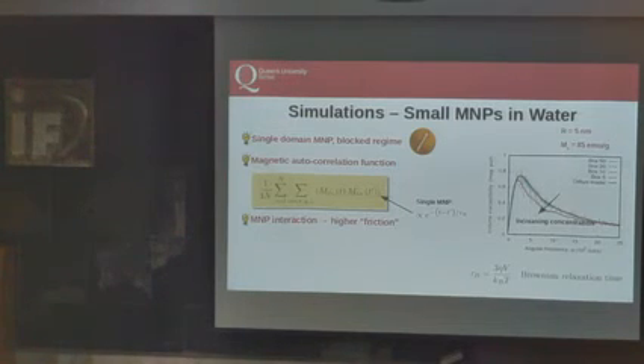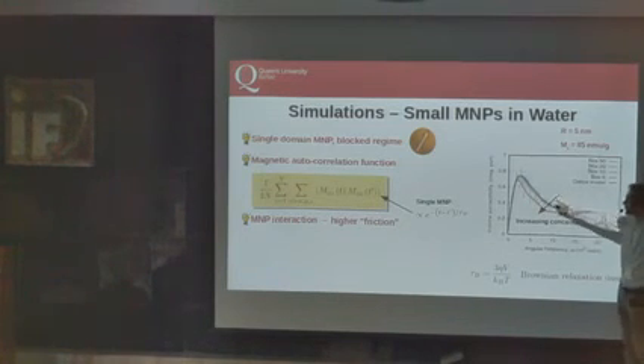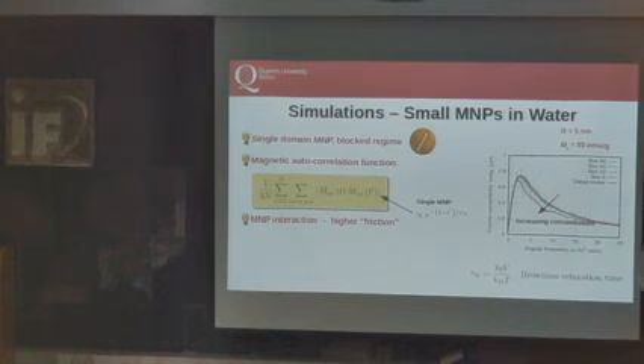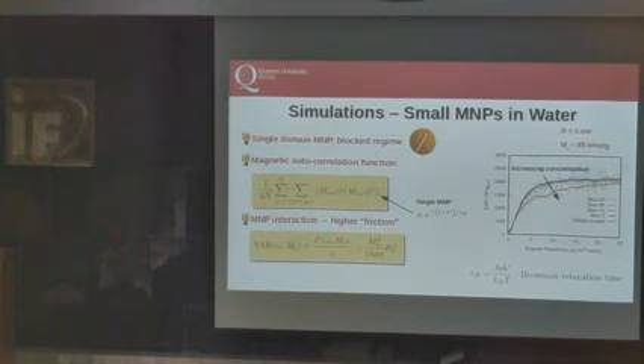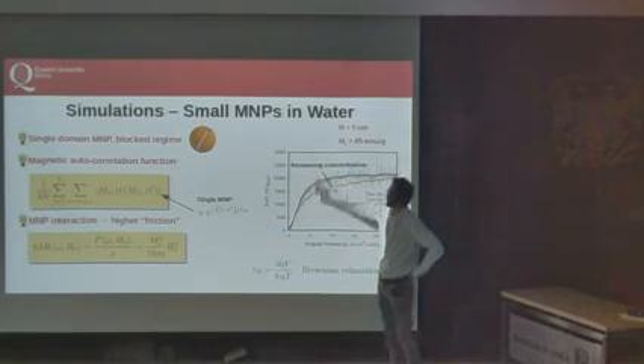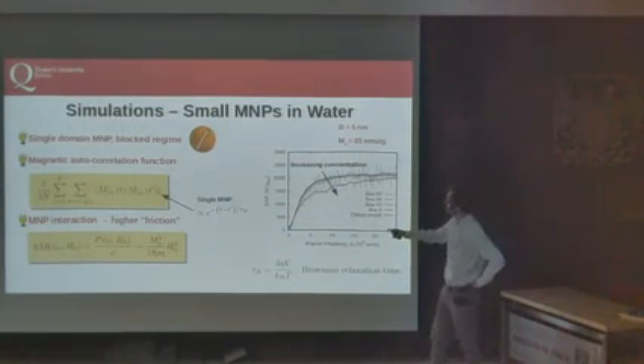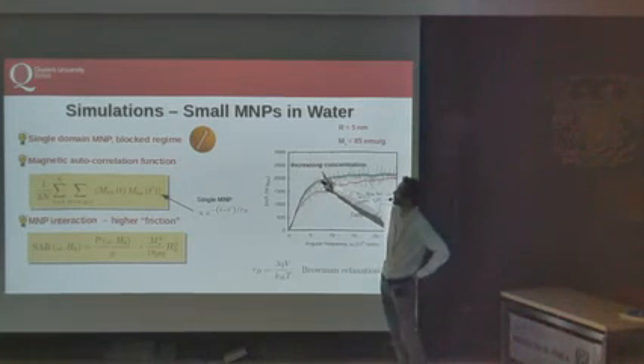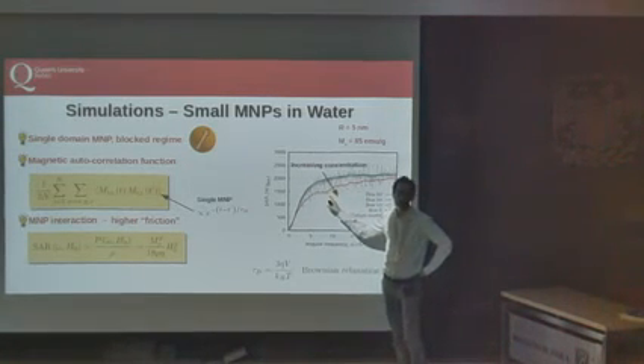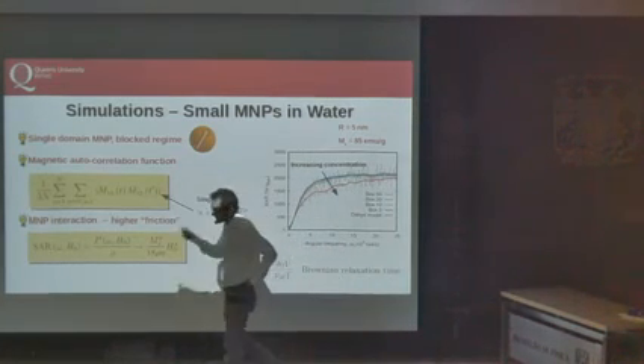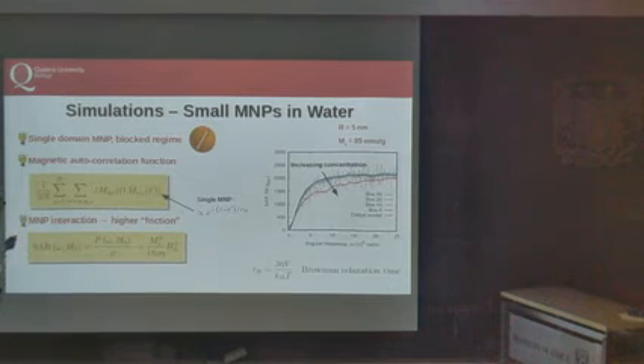From this we can obtain the imaginary part of the susceptibility, which is decreasing with the concentration. So this suggests that the higher the concentration, the lower is the SAR. Is that true? Yes. For the small nanoparticles, from molecular spin dynamics calculations, the effect of the concentration is to decrease the SAR. And to some extent, we can still use the Brownian expression or the Debye expression for the susceptibility. We just have to use an effective friction.